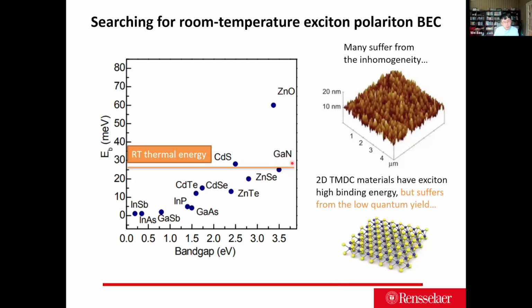However, to demonstrate room temperature exciton-polariton BEC, you need a system that has a stable exciton against thermal fluctuation. For room temperature, the thermal fluctuation is about 26 meV, milli-electron volts. And there are many inorganic systems that don't sustain this room temperature thermal fluctuation. That means if you don't have a stable exciton, you don't have exciton-polariton for you to emulate a lot of these cold atom experiments.